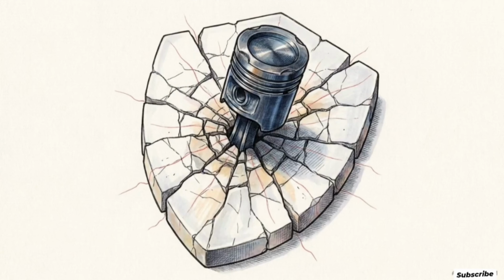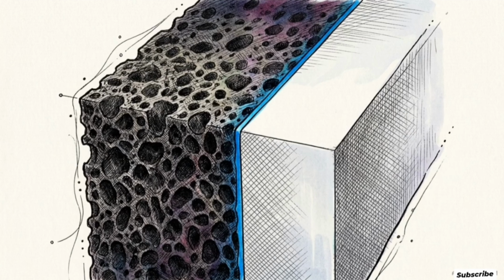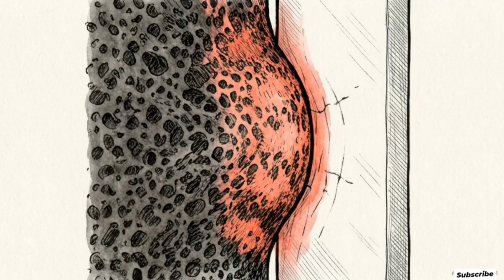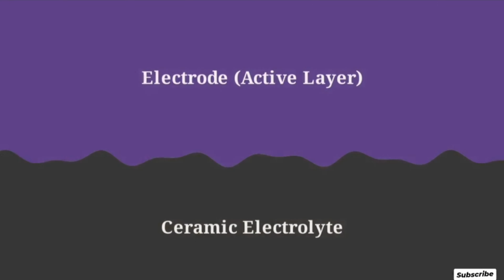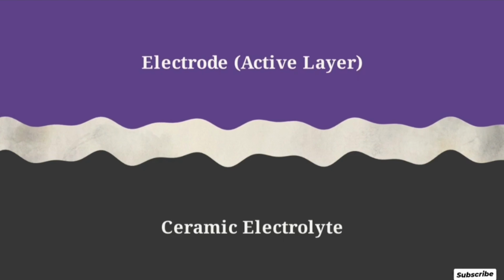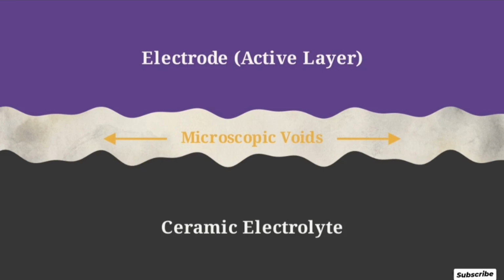The exact feature designed to make these cells safer, their absolute rigidity, is the same property that causes them to fail. To see how this happens, we have to look at the exact boundary line where the expanding electrode meets the solid ceramic electrolyte. In this cross-section, when the cell discharges, the electrode shrinks and pulls back. The inflexible ceramic cannot follow, leaving microscopic voids along the seam.